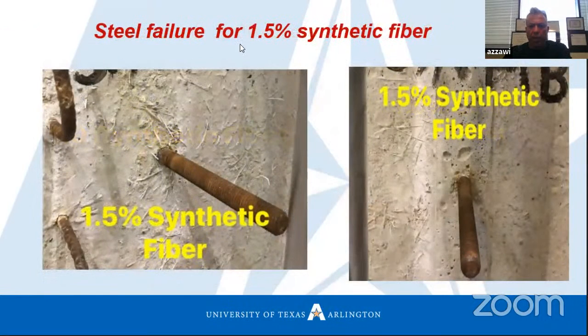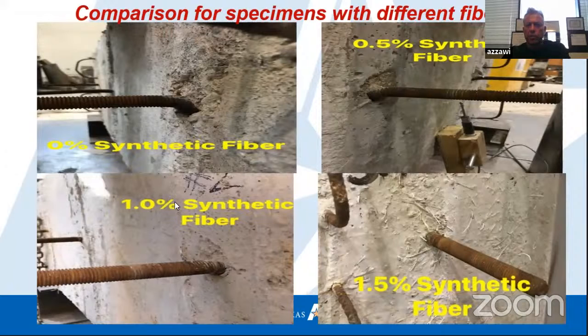With 1.5% we don't have any damage in the concrete, just a small portion around the anchor bolt, but we have shear failure at the steel itself. The anchor cannot resist more shear. This is the comparison of specimens with different fiber dosage. This is 0% fiber, plain concrete. This is 0.5%, and we see a big damage area here. With 1% we have less, and with 1.5% normally we don't have concrete damage, just a small portion around the bar itself.